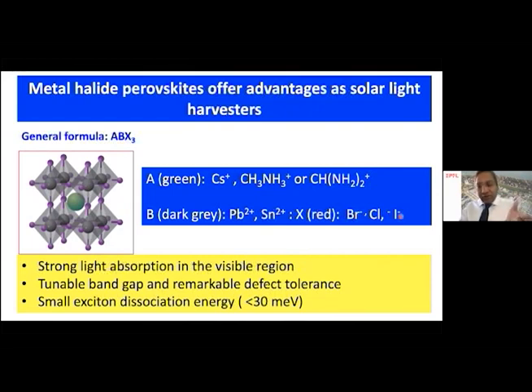If we use iodide, the band gap is too narrow. If we use bromide, it's an intermediate band gap, which gives you a green emission. If you use chloride, the band gap is too large. It gives you the blue emission. So this way, you can tune the band gap of these materials by changing the halides.